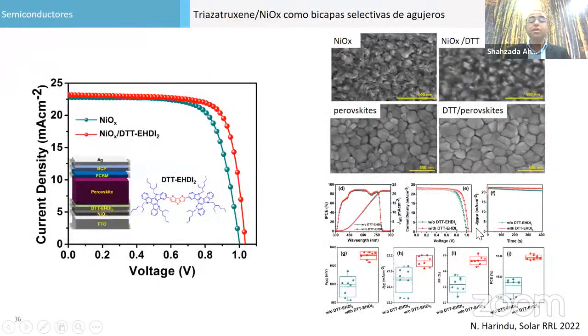So we published it. We also played with nickel oxide, the inorganic HTM, to increase the stability. This is the nickel oxide as such. We put a very thin layer of organic semiconductor here. It fills all this to form a uniform thin film of nickel oxide. It gives very good performance and very good stability with nickel oxide and organic HTMs. So it's a bilayer of HTM, a very thin layer of organic, and 50 nanometers of nickel oxide.